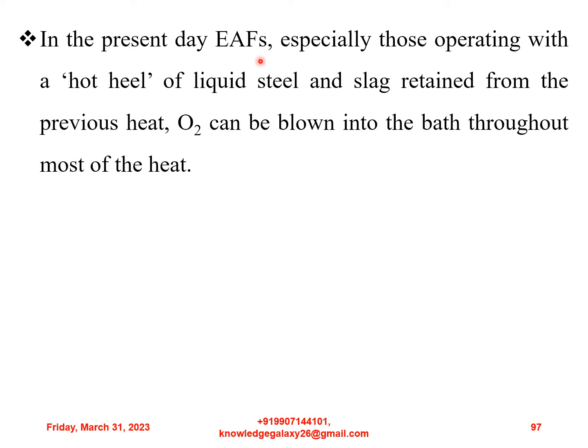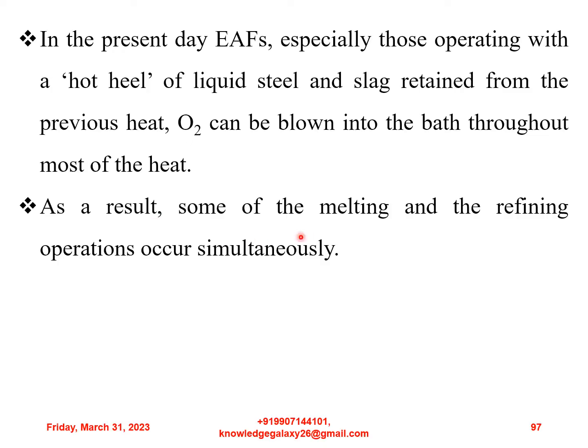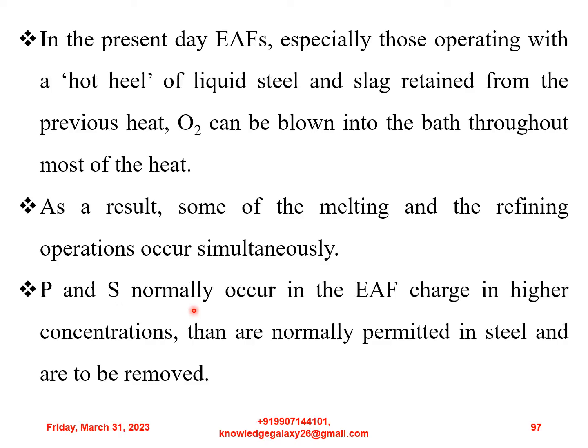In the present day electric arc furnaces, especially those operating with a hot heel of liquid steel and slag retained from the previous heat, oxygen can be blown into the bath throughout most of the heat. As a result, some of the melting and the refining operations occur simultaneously. Phosphorus and sulfur normally occur in the electric arc furnace charge in higher concentrations than are normally permitted in steel and are to be removed.